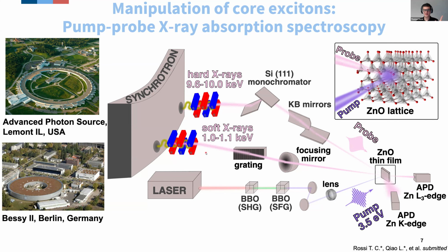Okay, great. So two answers, because these are two different experiments. For the experiment in the hard X-ray range, the sample is in air, and we are blowing nitrogen on it while we are measuring. And the experiment was done at a sufficiently low repetition rate that the lattice heating can recover between two consecutive pulses. For the experiment done in the soft X-ray range, this experiment is under vacuum.